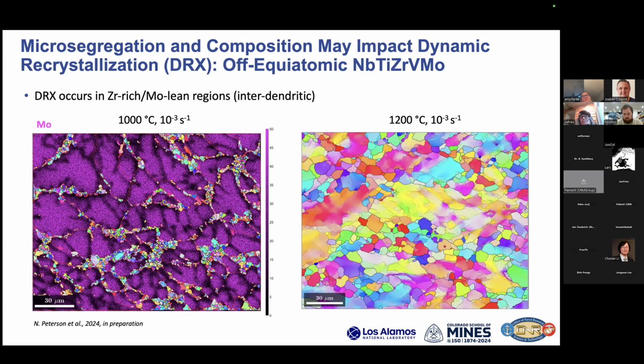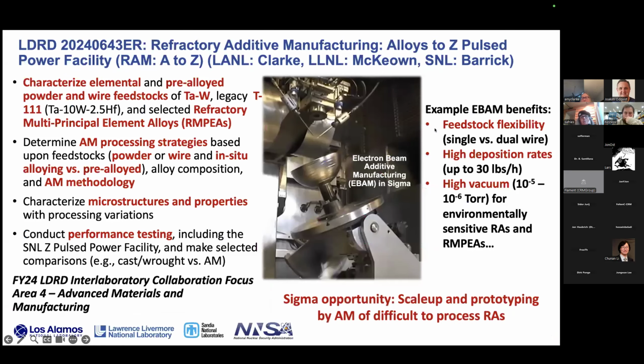So we basically have a strength differential that we set up between those two regimes in the microstructure, and that starts phenomena like DRX with deformation. And that could even be important for things like, say, we build something with additive manufacturing, and now we want to go ahead and heat treat it. So I think that there's a lot to think about still in this space about living with some of the microsegregation that we develop during solidification and what that means for any downstream processing that we might do. In this particular case, we were actually able to recrystallize this alloy.